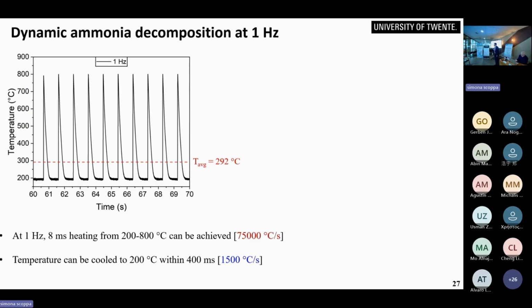So this is how this process works. We provide electrical pulses that are very, very short and very, very large, sufficiently large to reach, let's say, in 8 milliseconds, from 200 to 800 degrees C. That's 75,000 degrees C per second. And we cool down at a rate of 1,500 degrees C per second. That takes about 400 milliseconds to cool back down to 200 degrees C. Then we calculate the integral temperature average of this system, and that's about 300 degrees C. This is a very important detail for you to keep in mind.